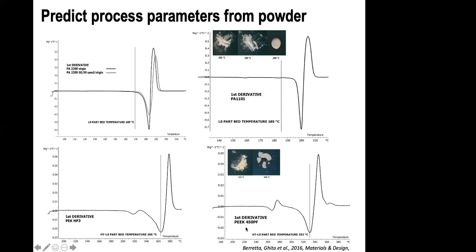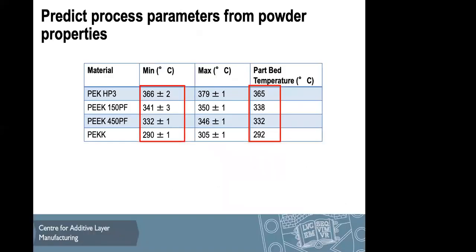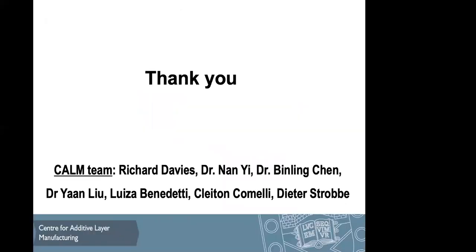In the case of the PEEK material, when we are at 332, which was well within the peak, at the minimum, the material was still in powder form, and when we reached 340, which was almost at the melting point, only then you could see a consolidation of the powder. So this is a unique, very interesting feature, which we came across during our study. And this brings me to the end of my presentation, and hopefully gave you a bit of flavor of the kind of investigation and work we do at Exeter.